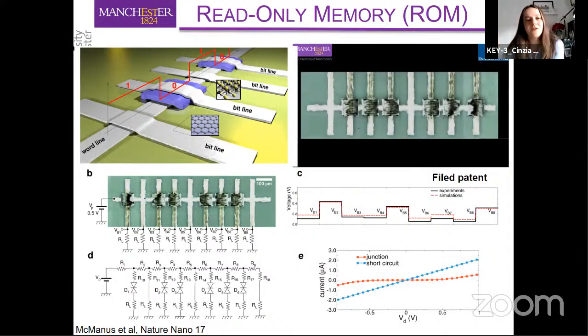And so, for example, let's have a look at this picture here. You can see that we have 1, 2, 3, 4 junctions. And in 2 of the junctions, we actually printed the heterostructure that I showed you before, which from an electrical point of view is a double diode. But then in these other 2 junctions here and here, we decided not to print the semiconducting layer. So effectively, we have a shortcut. So now we have 4 junctions where we have 2 different electrical components, the shortcut and the double diode.